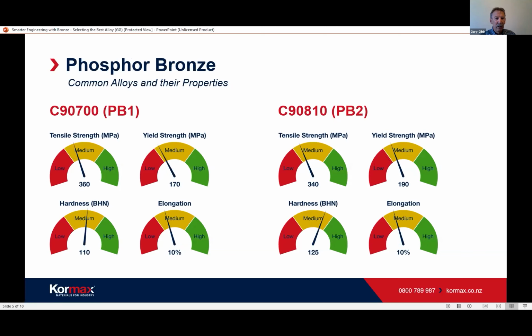The next one covers the phosphor bronzes, and they are generally high tin. So they're around 10 to 12% tin, and the balance copper, with a bit of phosphorus, generally around 0.5%. They're called phosphor bronzes. They're also called gear bronzes. Now, some years back, the LG2 or the gunmetal was also called phosphor bronze. That's not technically correct, but at the time it was called phosphor bronze, and that still hangs around a wee bit today, you see it.